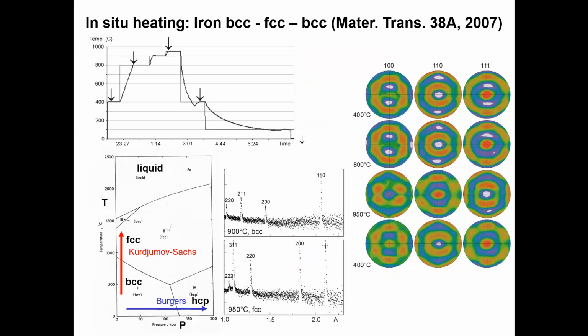So texture analysis, now what is remarkable in HIPPO, that we can heat samples in situ and look at the texture changes. And we applied this to iron, which is BCC at low temperature, and heated it to 800 to about 1,000 degrees, and then it became FCC and cooled it again. So you see how the spectrum changes, and then how the texture changes.